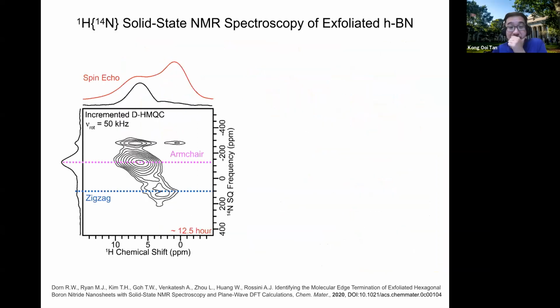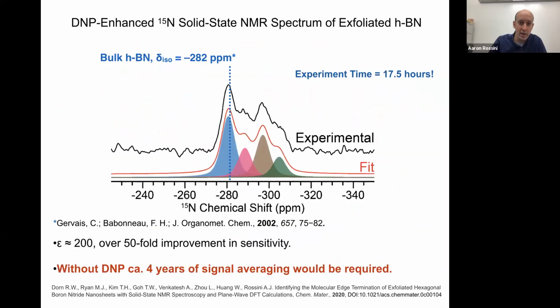One thing that really helped the boron experiments on the HBN is the boron T1 is actually extremely long in that material when it's not oxidized. If you look at the pristine material, you have a boron T1 of like 140 or 200 seconds at room temperature. So it's actually a really nice material to do direct boron DNP. I suspect that long T1 and the boron spin diffusion helps give you a reasonable DNP enhancement.